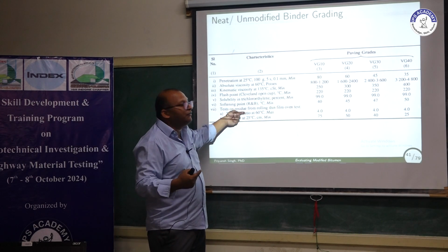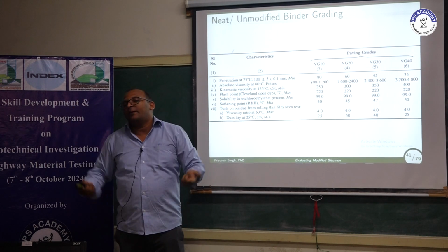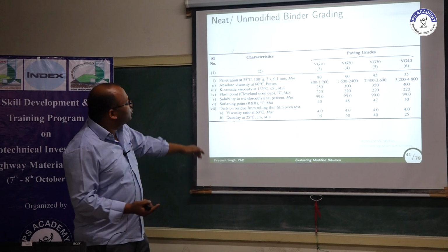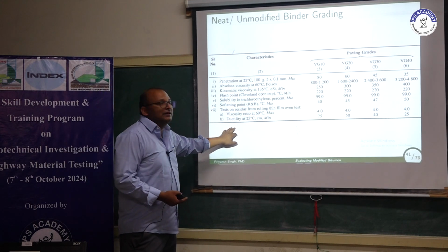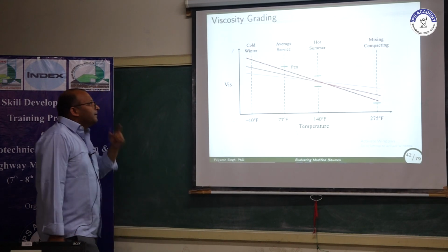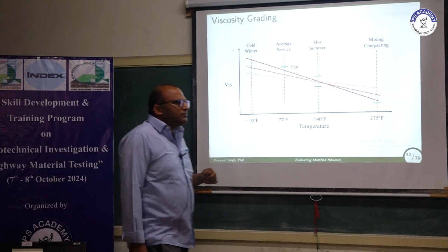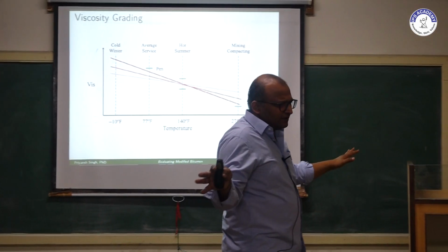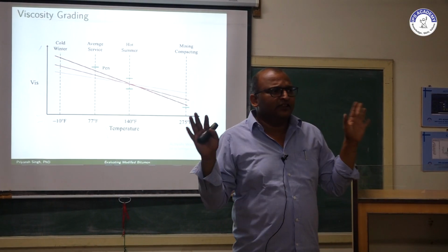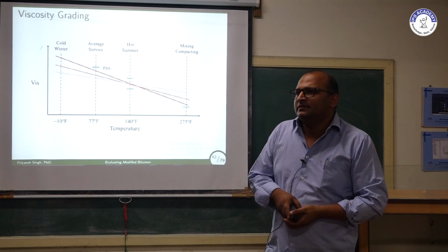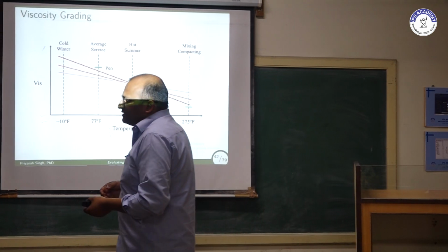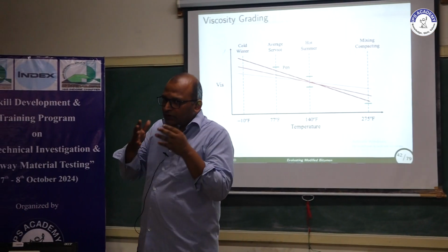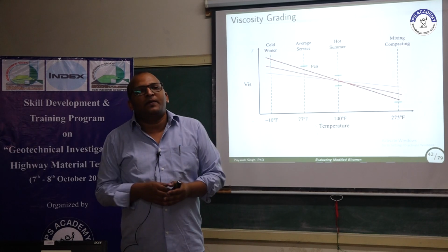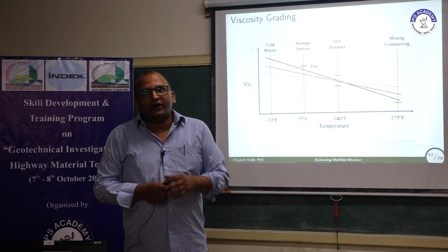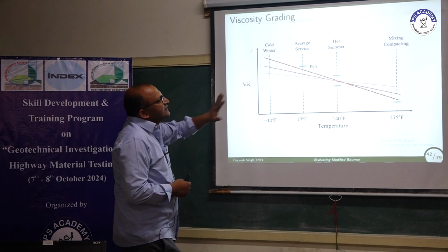So these 2 tests you have to do on the short term aged samples, not on the neat samples. So those are the viscosity ratio and the ductility. Now we have done this grading very well. We have VG10, 20, 30, 40 binders. But whether these gradings are fair enough to separate out the different types of binder, to understand, let's see this graph.